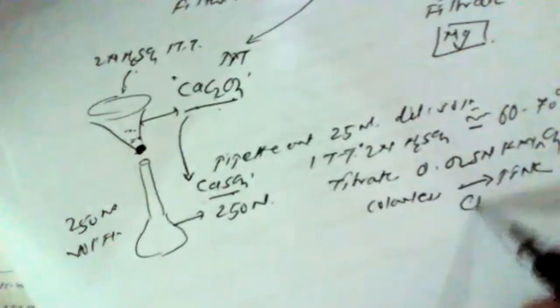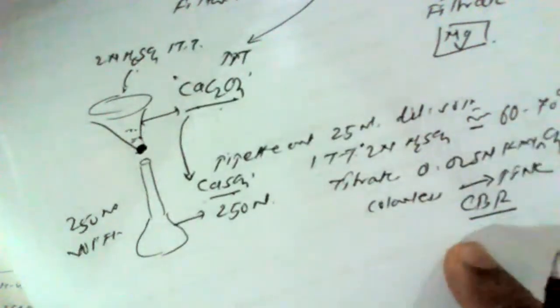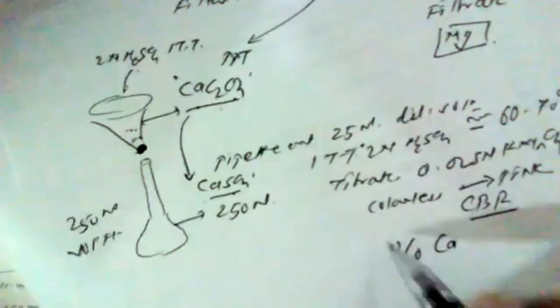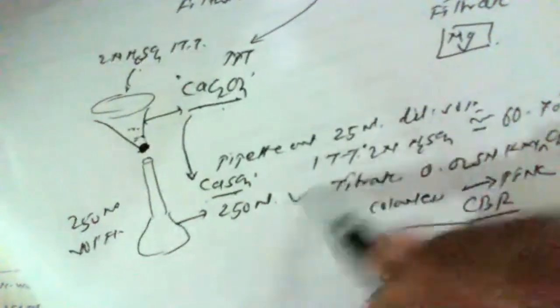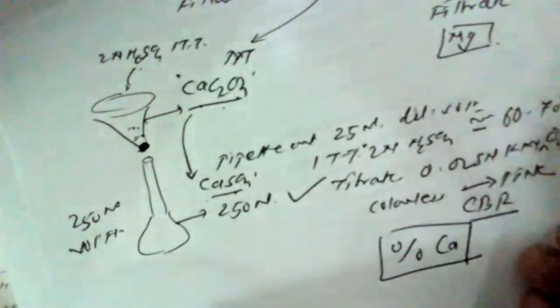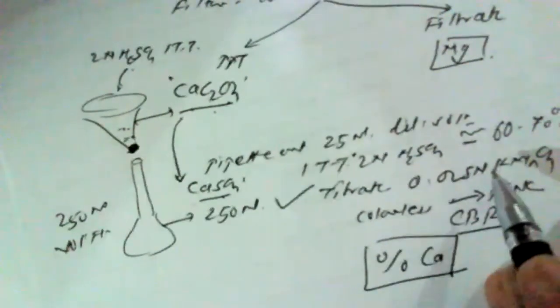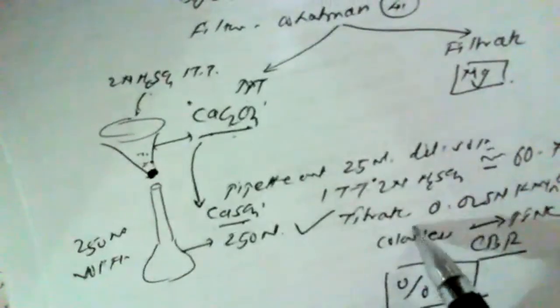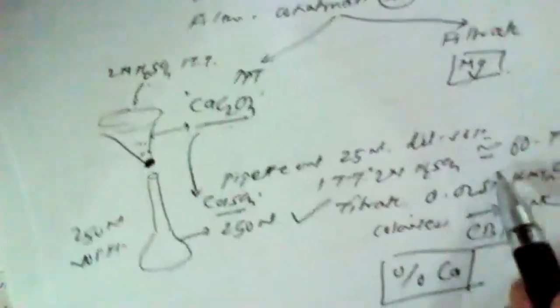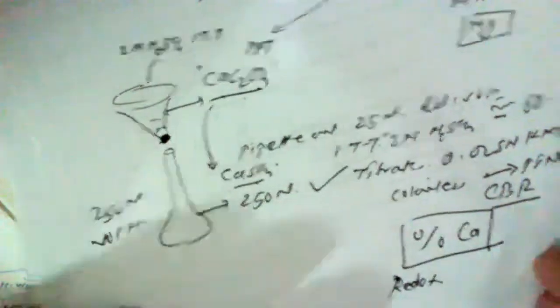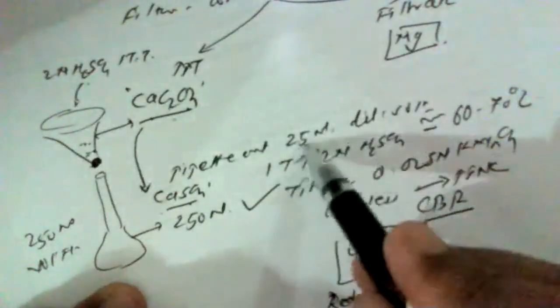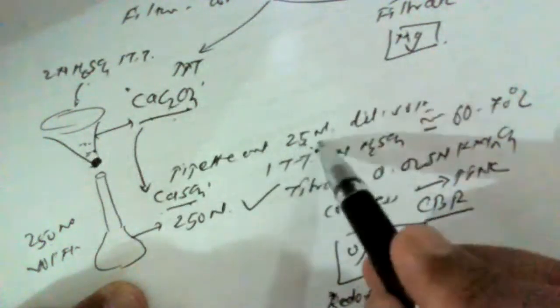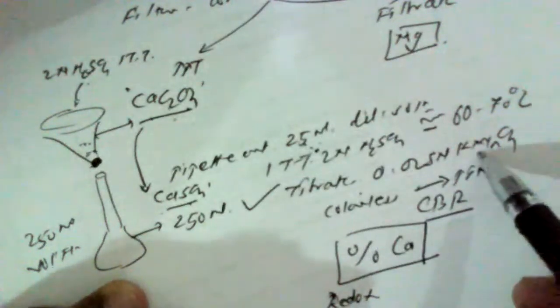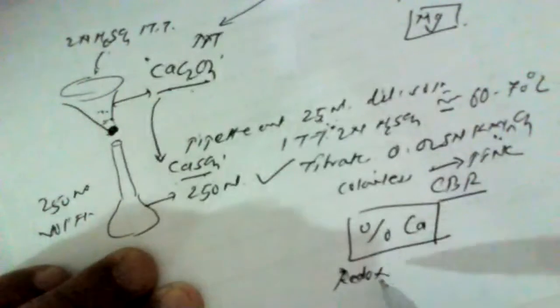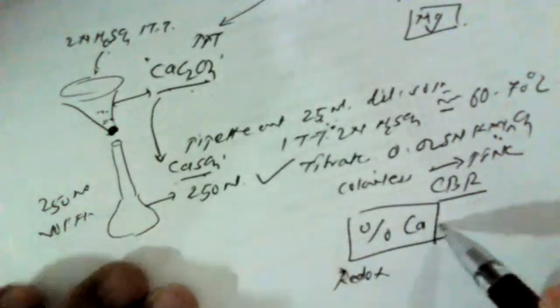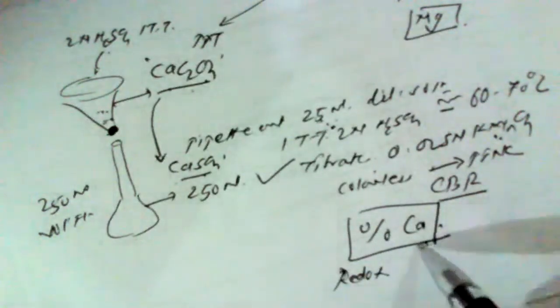So here, by using the constant burette reading for this calcium sulfate solution, we can calculate the percentage of calcium in the dolomite ore. This procedure is what we followed at our BSc part 3 level, that is determination of oxalato group from the given solution of potassium trioxalatoaluminate. So the oxalato group reacts with this KMnO4. This is an example of redox titration. Here the 25 ml solution that we have taken in a conical flask acts as a reducing agent, and KMnO4, which is taken in a burette, acts as an oxidizing agent. So it is an example of redox titration. By knowing the constant burette reading, we can calculate the quantity or the percentage of calcium in the dolomite ore.